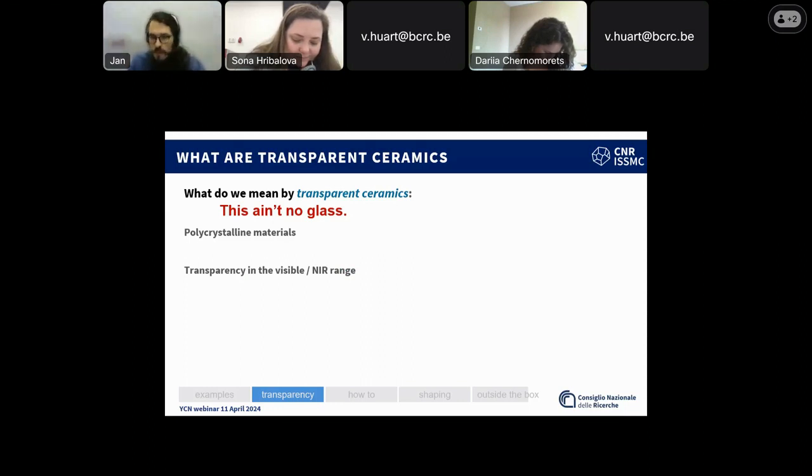And for example, here, these are some materials for lasers, where you have one part, the one with the green color, doped with the laser ion, and the other part that's not. This actually is helpful in one case because the part without dopant has a higher thermal conductivity, and so you can cool better.